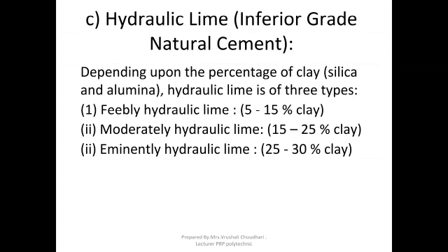Feebly hydraulic slaking takes place within 50 to 60 minutes, moderately takes 1 to 2 hours, but eminently hydraulic is difficult to slake. For setting, feebly hydraulic takes approximately 3 weeks, moderately sets within 1 week, while eminently takes 1 to 2 days, just like cement.